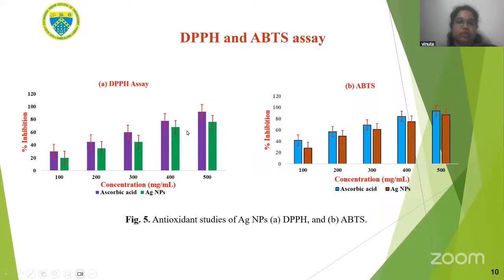So this is the antioxidant result of the DPPH assay. From these results, we can tell that the synthesized nanoparticles show good antioxidant properties, even though they show slightly lesser antioxidant property than the standard ascorbic acid. Here this is the ABTS assay. Here also we have used the same concentration, 100 to 500 microgram per ml. For all the assays we have used the same concentration, just to check how that varies with the different assays. In this assay also we have used ascorbic acid as a standard drug. Similar to the DPPH assay, in the ABTS assay the silver nanoparticle shows slightly lesser activity compared to the standard.